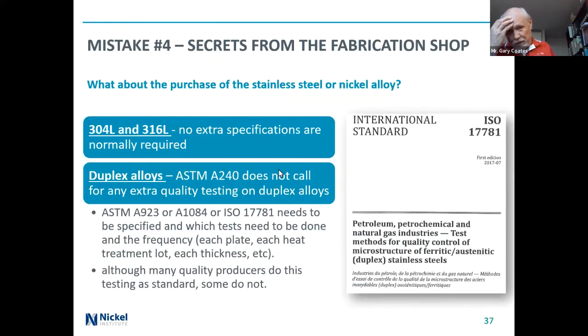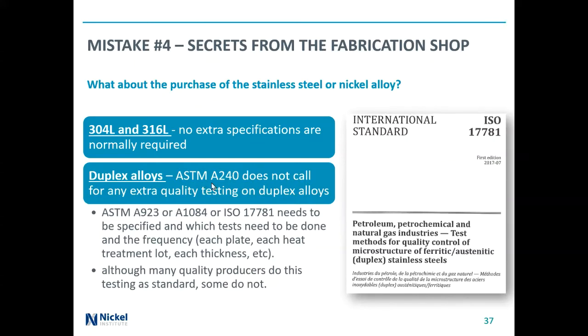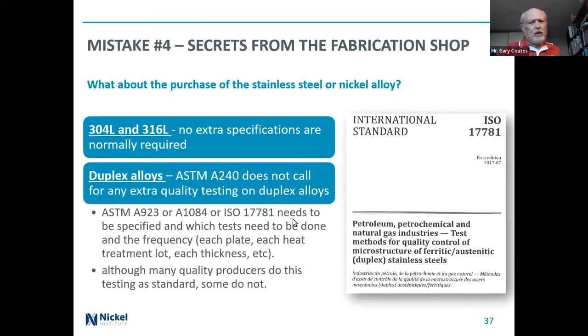So let's talk about the purchase of the stainless steel or nickel alloy. Typically for 304L, 316L, there are no extra specifications required. But for duplex alloys, the standard ASTM A240 does not call for any extra quality testing on the alloys. You have to specify it extra, whether it's the A923 or A1084 or the ISO 17781. They all need to be specified, and even which tests need to be done, so it is very clear. And although many quality producers do this test as standard, some do not.